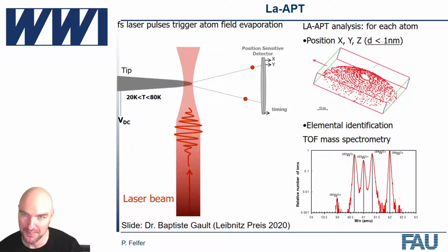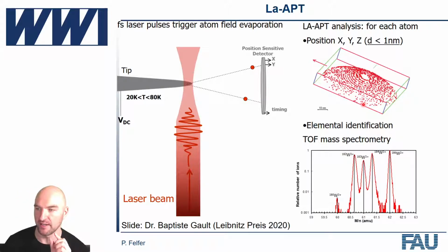Anyway, this is sort of the limitation. What that means is that the uncertainty in allocation of the flight time to the mass-to-charge is constant with respect to the pulse. So the longer your flight time is, the better the ratio of time of flight to uncertainty in time of flight becomes.